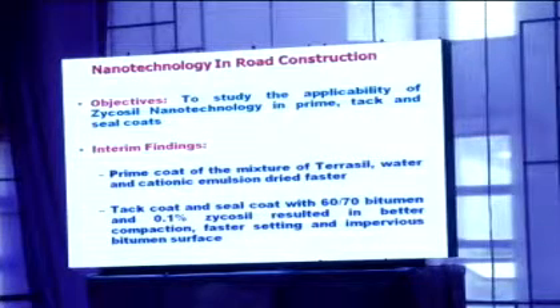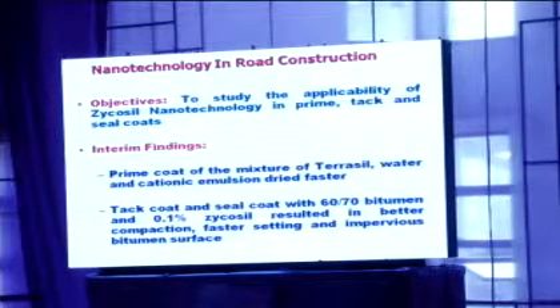This is another project which has been reported using the same Zycosil materials, nanotechnology in road construction. It has been observed that when Zycosil is used in bitumen for prime coat, tack coat and seal coat at the rate of 0.1%, it results in better compaction, faster setting and an impervious bituminous surface.